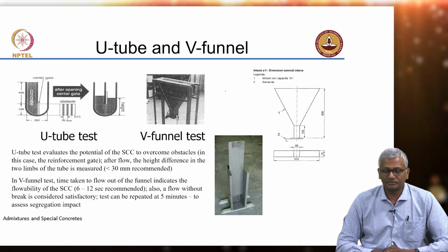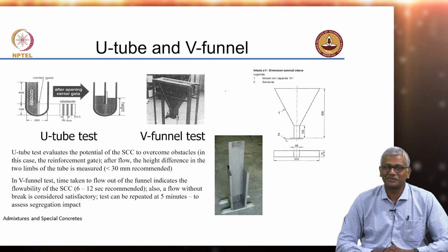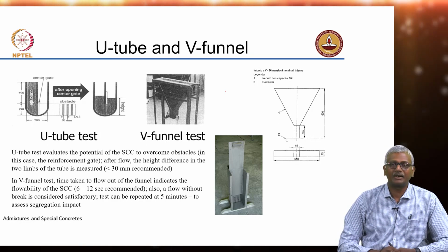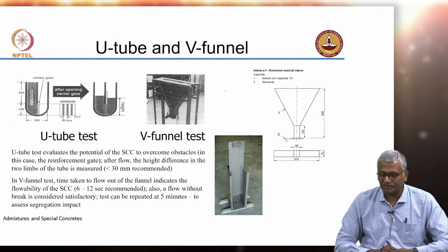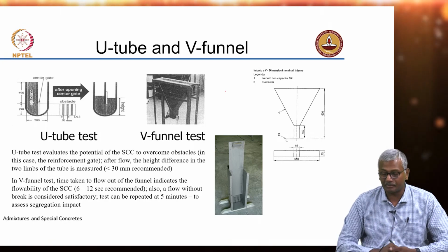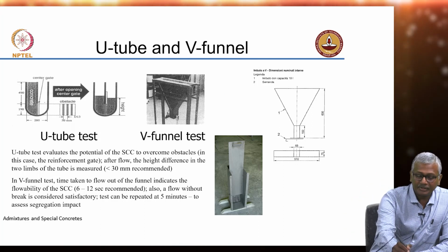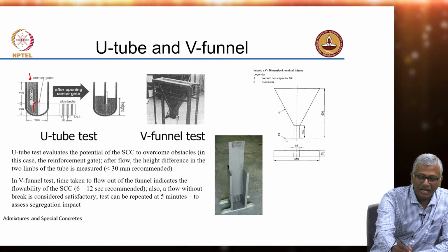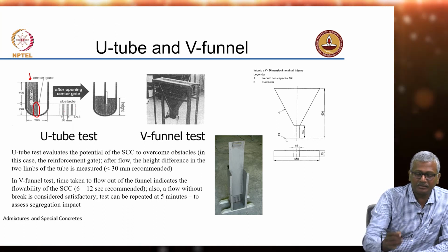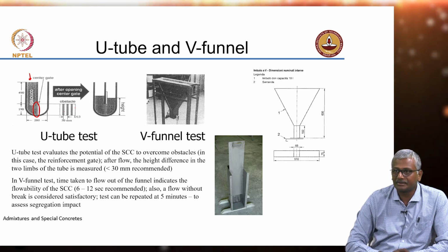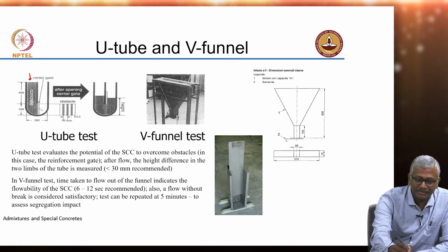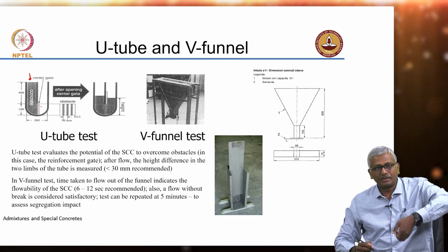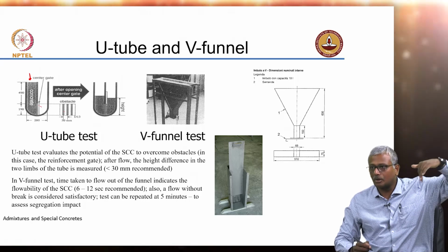The U-tube and V-funnel, as I said, are primarily looking at not just flowability, but also addressing some level of passing ability. In the U-tube, you have a tube shaped like a U. You fill up concrete on one limb of the tube, you have your obstacle in the form of reinforcements placed in the center, and you have a center gate which is preventing concrete from moving. Then you lift the gate and the concrete will start moving.